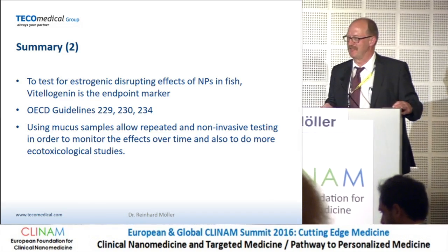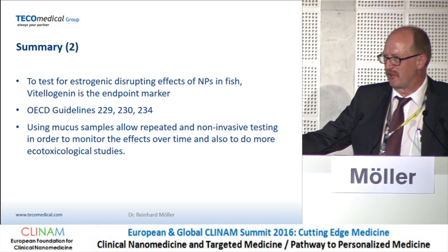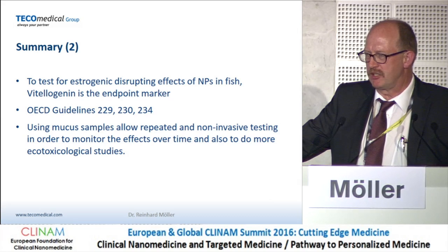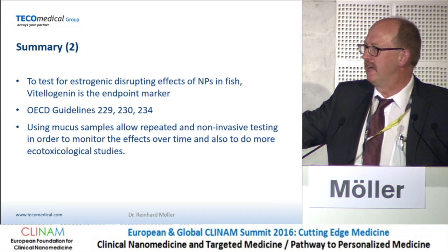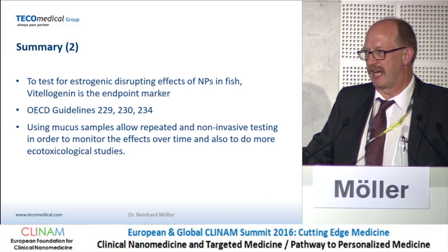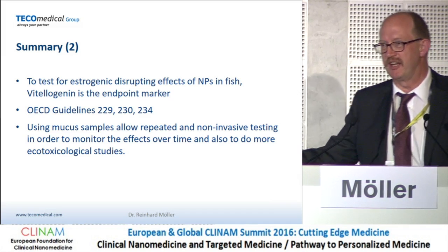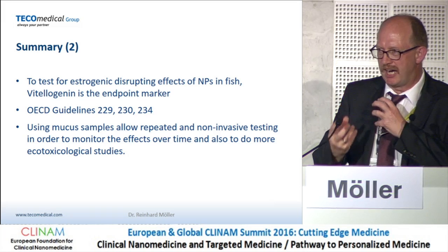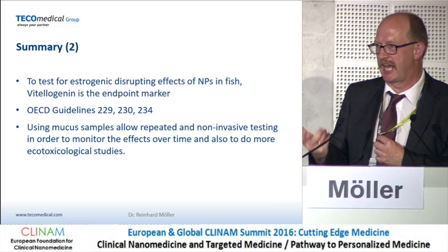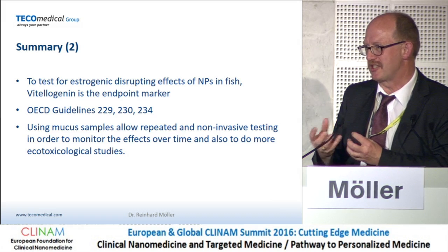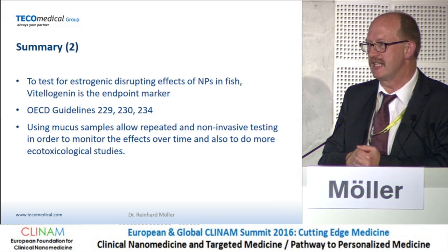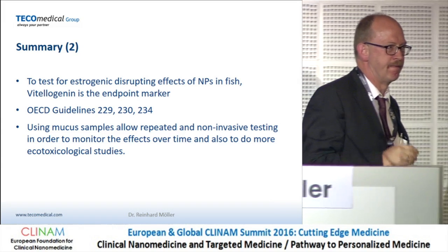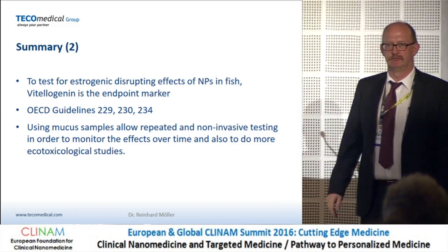That's easy. Basically, I was referring to a study from the United States where they found nanoparticles. There was recently a publication showing that nanoparticles will be modified in the environment. So this is another concern: if nanoparticles are highly reactive and go, for example, into the sediment, they might change their properties due to temperature and pH, but also become covered with proteins or something like that. They might also form aggregates. That's what was reported and documented. Thank you very much.